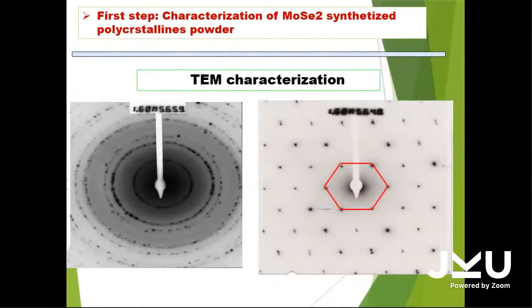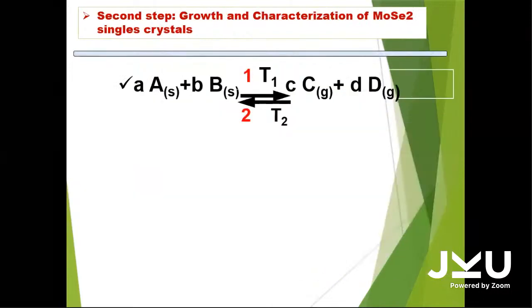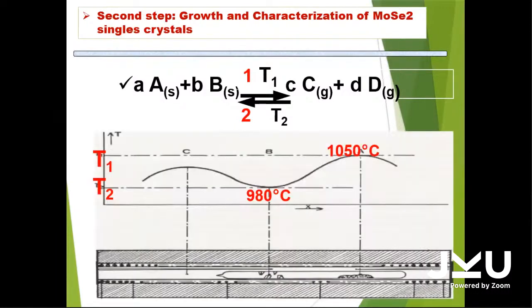After this characterization, the second step is to use this powder to grow single crystals. The powder is introduced into a tube in which the transfer agent is added. The tube is closed under high vacuum and then introduced in the growth oven. The end containing the products is placed in the hot zone while the other end is placed in the cold zone, as shown in the figure. Growth takes place for 5 days, then it is allowed to cool for 1 day. The single crystals are recovered and then analyzed.